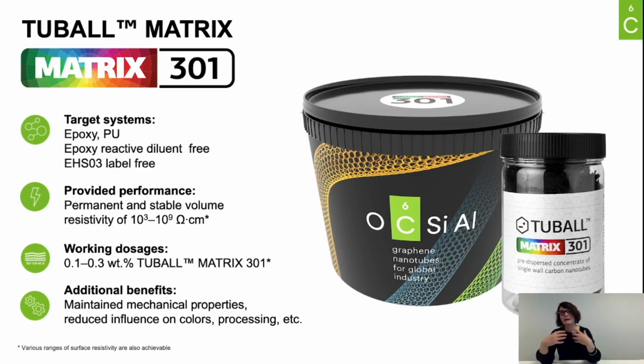And the working dosages are very, very low. So we speak about 0.1 to 0.3% of TUBALL Matrix 301. But if you remember what I said previously, these are 10% concentrates. So in reality, in your final system, the TUBALL loading will be 0.01 to 0.03%. It is as minimal as that.